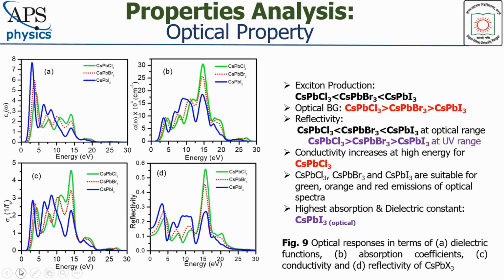The highest optical absorption and dielectric functions is observed for cesium lead iodide indicated by the blue lines. The reflectivity order follows the opposite trend for low energy region and ultraviolet region. Conductivity increases at high energy side for cesium lead chloride. Cesium lead chloride, bromide and iodide are suitable for green, orange and red emission respectively.